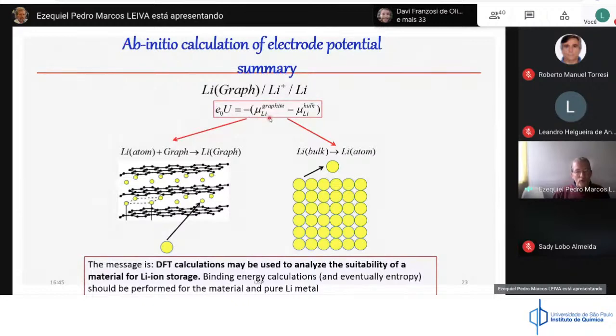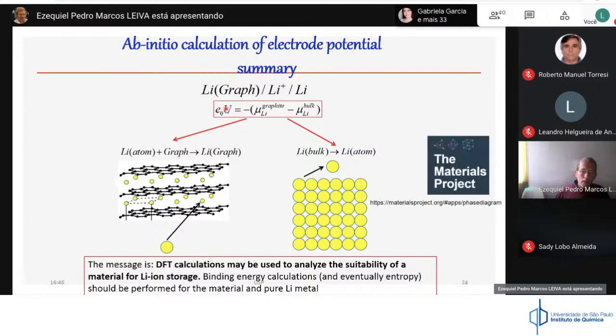What you have to do is to make one calculation for the insertion of a lithium atom in the material you have under study, in this case graphite, and you have to insert a lithium atom in the bulk material, and from this you can get the theoretical potential difference of the cell. This works pretty good. And if you are interested in that, you can take a look. I always advise to take a look at this page. This is the Materials Project, which was headed by Gerbrand Ceder, and they made a lot of calculations for many materials. So if you are interested in a given material, you can go there and look inside, and you will find